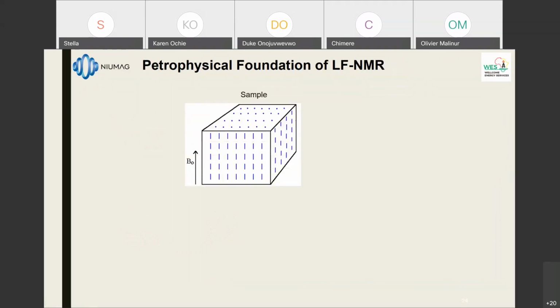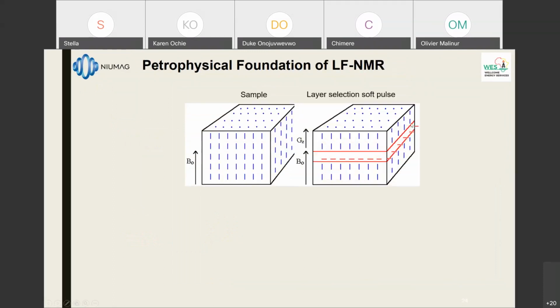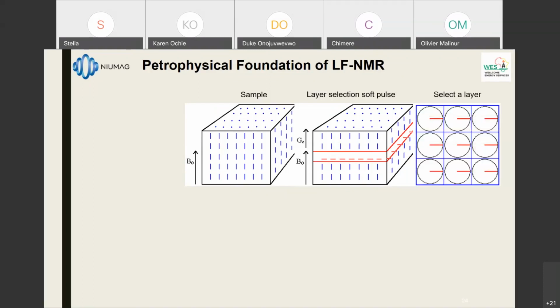So this is our sample. Our sample is inside a magnetic field, and you see we have all the spins which are aligned like this. Now, if we put the magnetic field, let's say 1.2 Tesla on top and 0.8 Tesla at the bottom, and at the same time we send the pulse, knowing that the radio pulse has a certain frequency, we will be able to excite only the place where the magnetic field is equal to 1 Tesla. Okay, you follow me? So what we will have done, we will have selected a layer in the core.